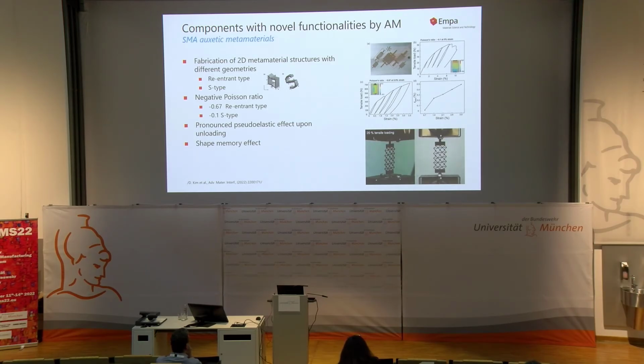So here are several examples of 2D metamaterials which are supposed to have negative Poisson ratios. We can easily print them, and we could show that we can maintain this negative Poisson ratio effect. Actually, those are meant for compression, but our colleagues also did tensile tests, and yeah, we see it ruptures. Doesn't matter, just go there also with the heat gun, and then you don't see the defect anymore after it's fractured. So it's a nice material. Of course, it doesn't have the load bearing capabilities anymore. But yeah, so we can make these metamaterials.